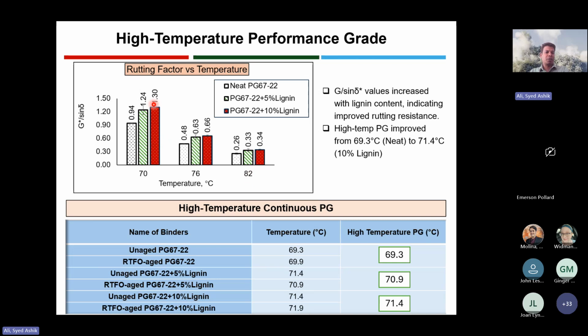As you can easily see from this graph, with the addition of lignin, 5% and 10%, we have seen an increase in the G star over sine delta value. And this trend is true for all temperatures, 70, 76, and 82 degrees. So it tells us that the rutting resistance of asphalt binder is going to improve with the addition of lignin. So we can expect some good rutting resistance with the higher amount of lignin.